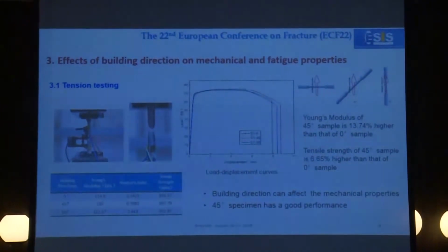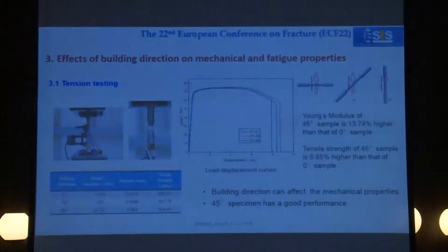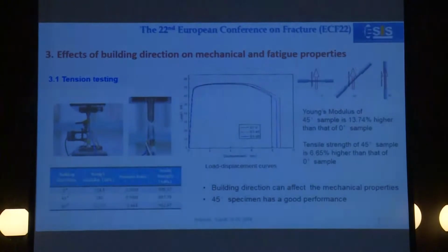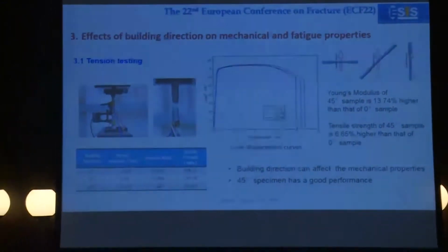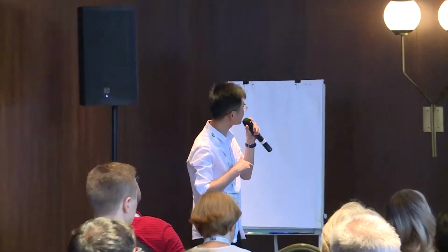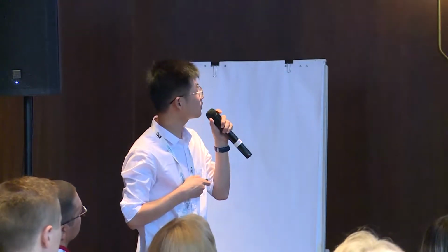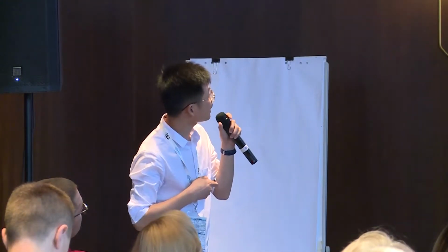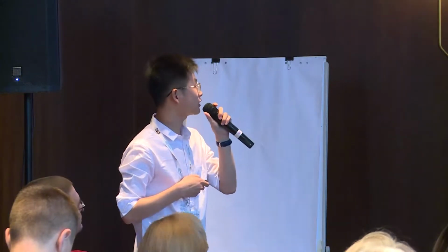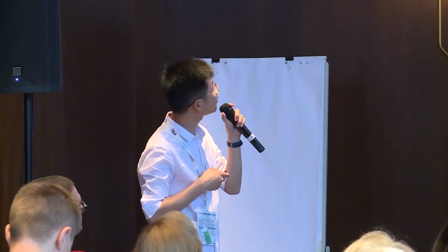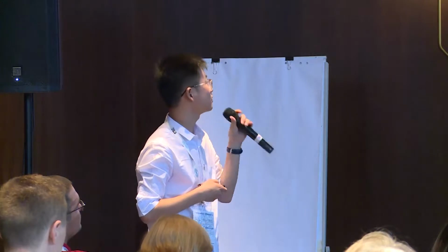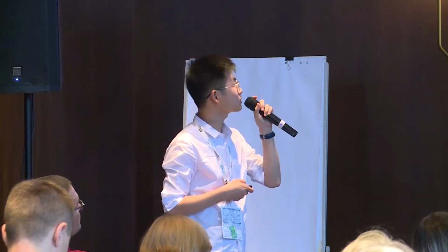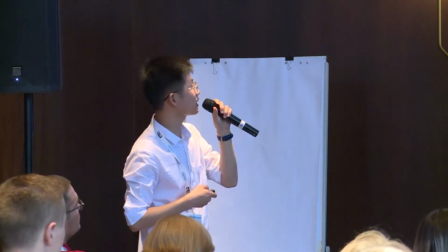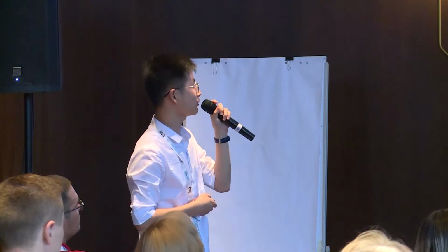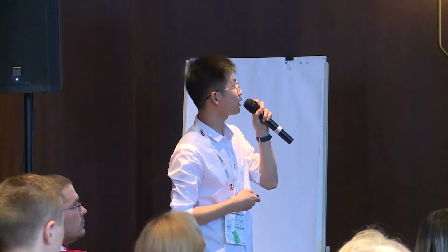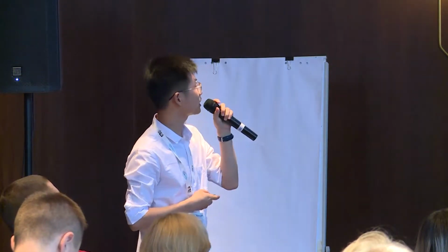In order to study the fatigue property, the tensile stress should be obtained at first, and we performed the tensile test. The test data is shown in this table, and these are the load displacement curves. From these curves, it's apparent that building direction can affect the mechanical properties. The 45-degree samples have a good performance. Young's modulus of 45-degree samples is 13.74% higher than that of 0-degree samples, and the tensile strength of 45-degree samples is 6.65% higher than that of 0-degree samples.